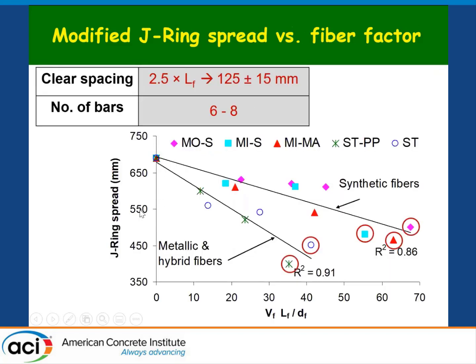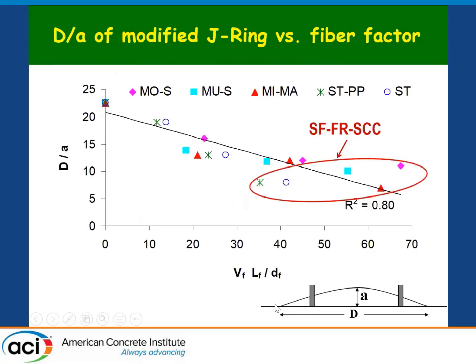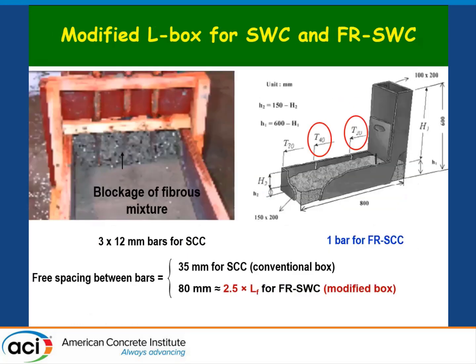And you can measure the diameter, and again you see that there's a separate relationship with synthetic and metallic. But we can also measure this ratio, which is the diameter divided by the mean height in the middle. And that can regroup really all the fibers, whether they're synthetic, hybrid, or metallic. So we call that a D/A. The mixtures highlighted here are those where the fiber content or the fiber length was so high that we got super workable concrete, so fiber reinforced super workable concrete, and we were not in the SCC consistency.